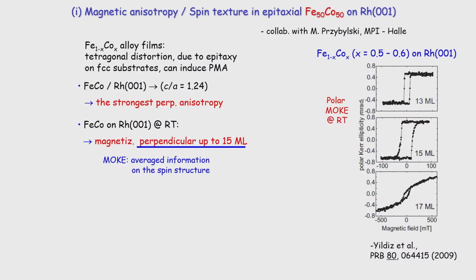And if you grow iron cobalt on rhodium, you see that by MOKE you will see that up to 15 monolayers, you have a polar MOKE, you have a square polar loop. That means you have perpendicular spins. But MOKE makes an average, okay?